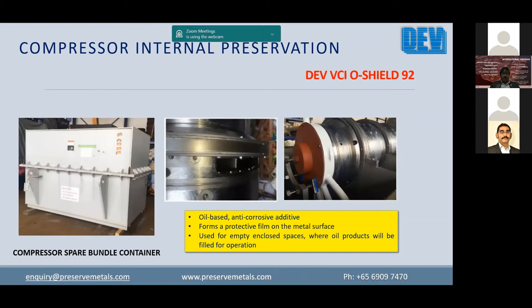The major advantage of this particular product is that once we use it for preserving the internals of any oil system, whether it's a lube oil, hydraulic oil, or a diesel or fuel oil system, it only forms an invisible monomolecular layer coating, as shown here. You'll be able to see the surface, and you can monitor the protective efficiency using a corrosion monitoring coupon. And finally, when you want to add the fluid, there is no need for any flushing, because this protective is compatible with the various oil-based products, so the client need not flush the system before he fills it up with the oil product.